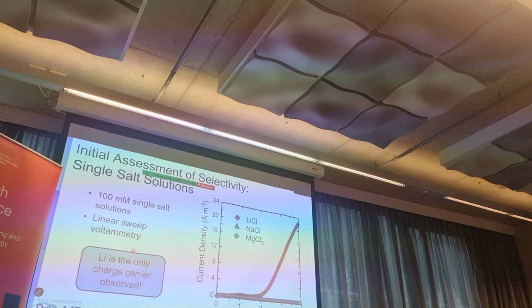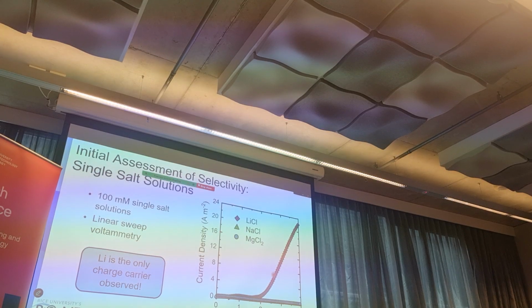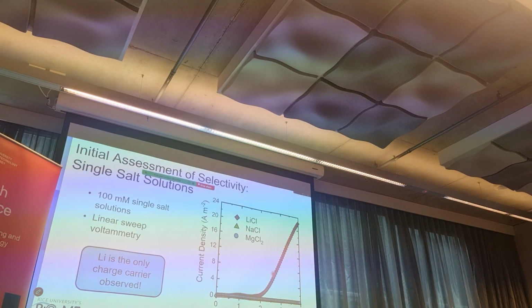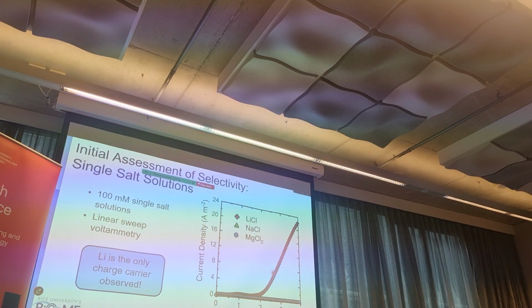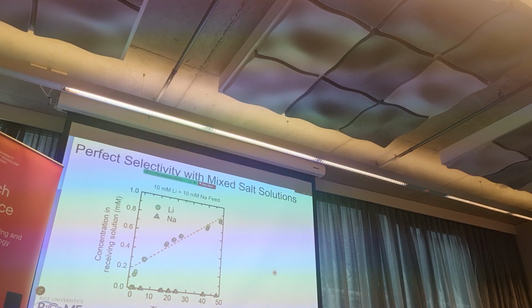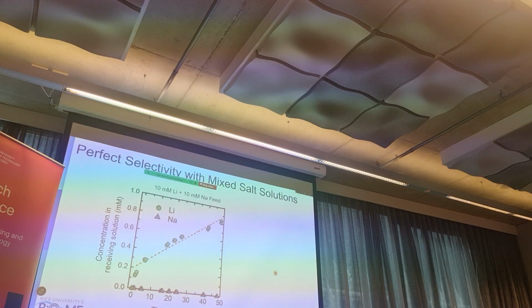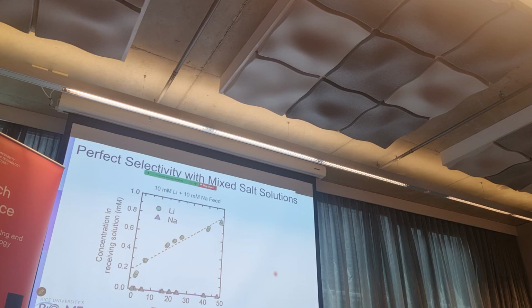So we can say lithium is the only charge carrier, the only one that can transport through this solid state electrolyte. But that's single salt, and we need to know what happens in a mixture. So we used a mixture with 10 millimolar lithium and 10 millimolar sodium as feed, and we see the same thing.